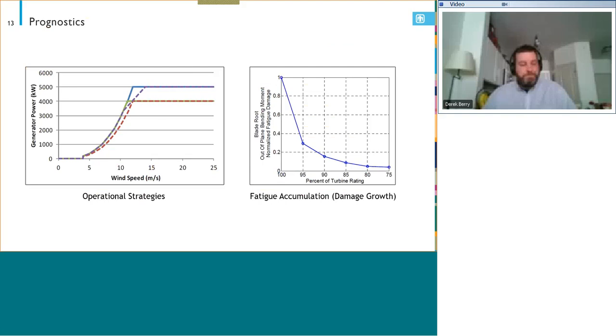So then what do you do once it's out in the field? This is also something that I would say is on the horizon for wind. If you understand that you do have a flaw, you do have some damage, it's not always practical to repair it immediately. So we and others have looked at different operational strategies whereby you might change the power output or the rating of the machine to slow the damage growth. That assumes you have very good knowledge of what the damage growth actually is, and I think the comment that was made earlier about AI systems, training them to understand a given platform and specific flaws and damage growth rates for those, is really important, and that's something that is also going on in the industry.